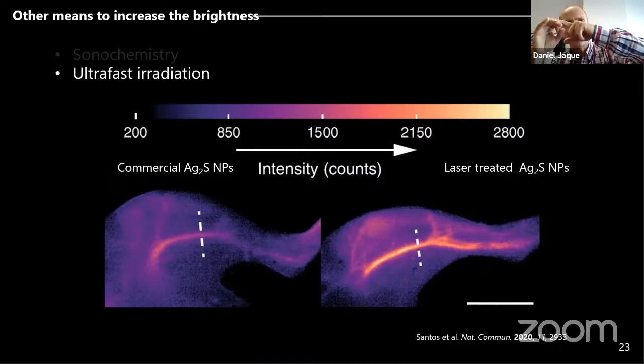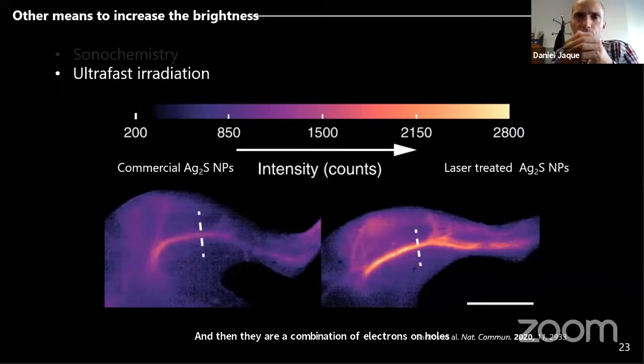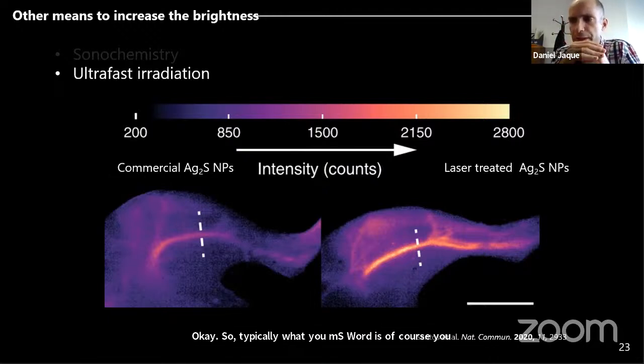And then the recombination of electrons and holes produces luminescence, and what you register is how fast that luminescence is, okay? Of course, you have to measure a number of events, but with this process, you excite the nanoparticles to the conduction band, and you measure how fast is the decay from the conduction band to the valence band. And then you obtain the fluorescent decay time, and you fit, and you obtain the lifetime.